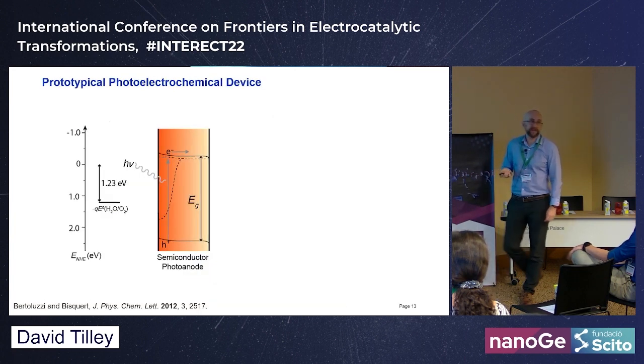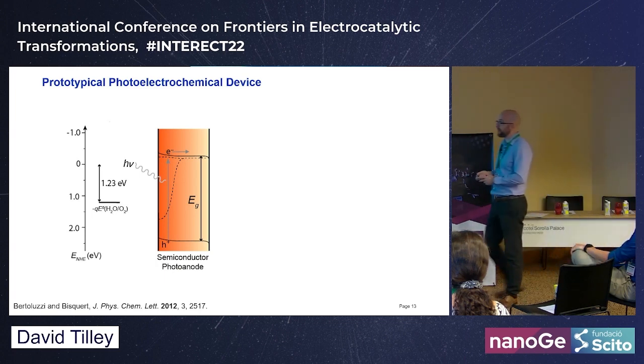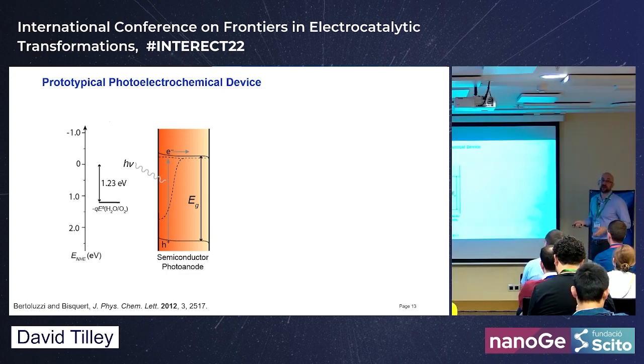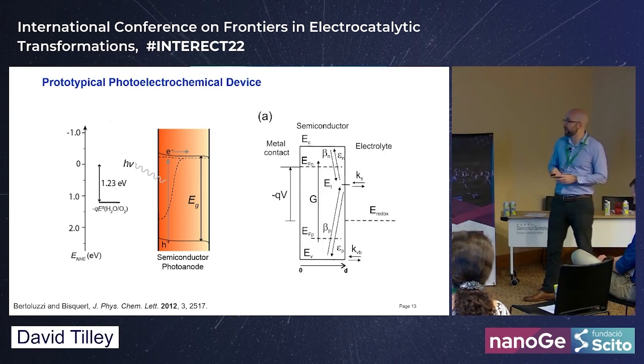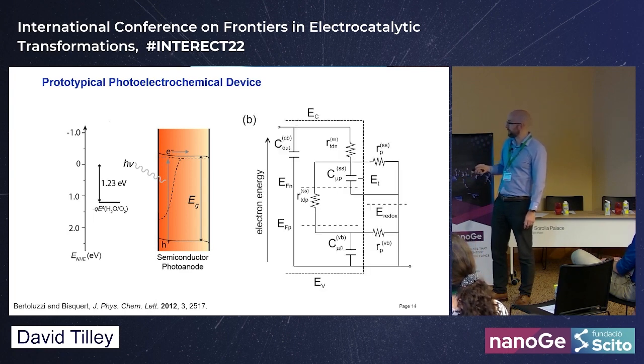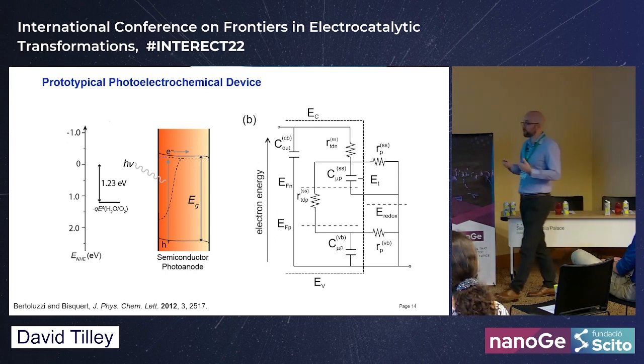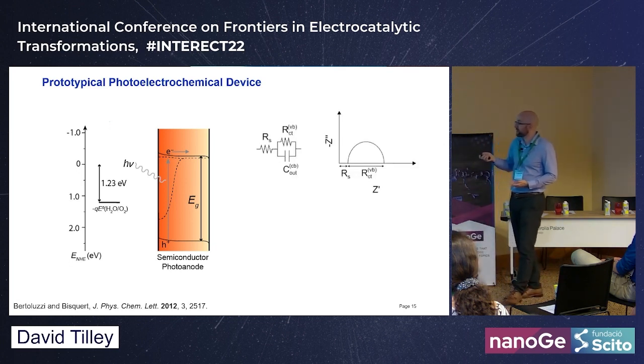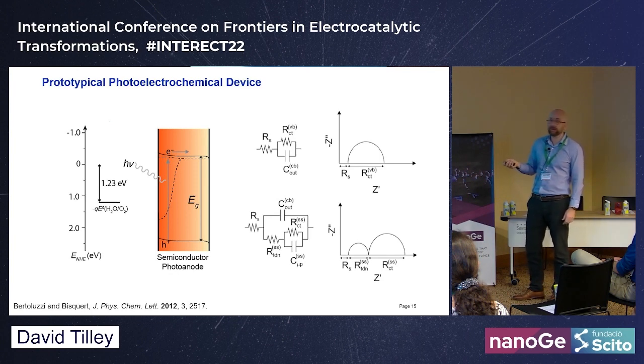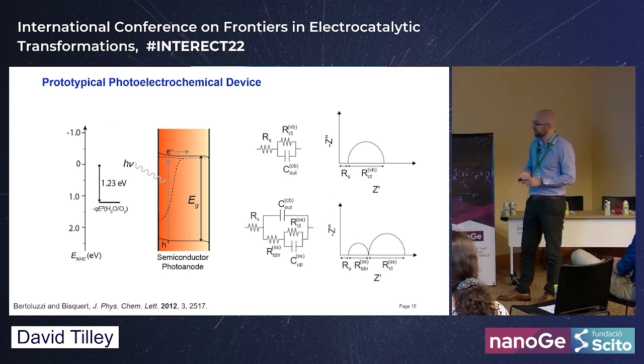Now I'll switch to impedance spectroscopy. Prior work was pioneered by Bisquert and colleagues and later Tom Hamann, looking at iron oxide — the prototypical single-material photoanode. Even this simple system has many photophysical processes: generation, trapping, and charge transfer. Although a full equivalent circuit gets very complicated, when you run impedance you typically see only one or two elements, collapsing the complexity into simple RC elements or nested versions.